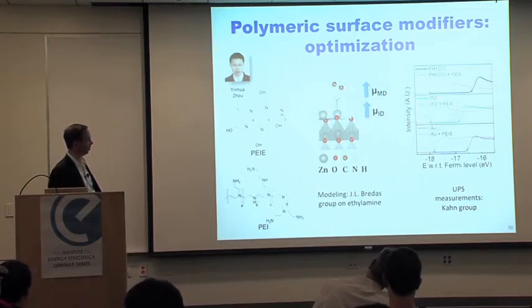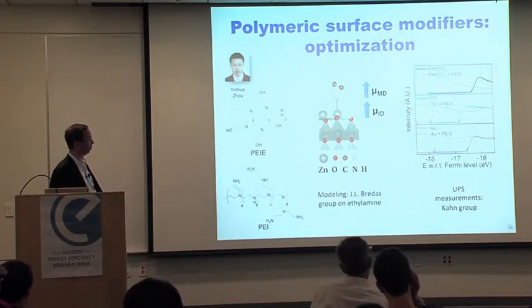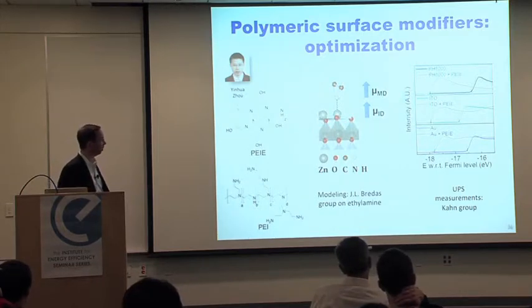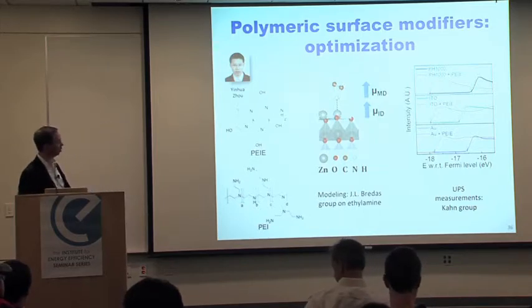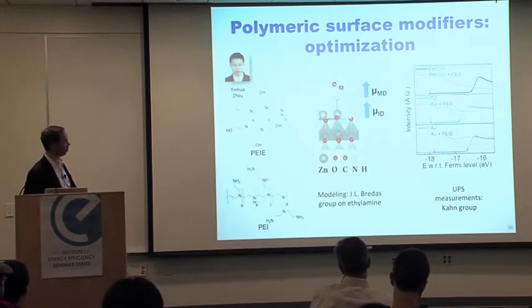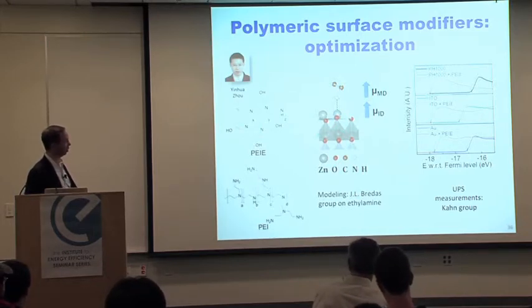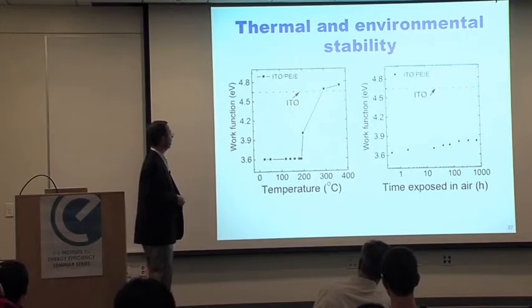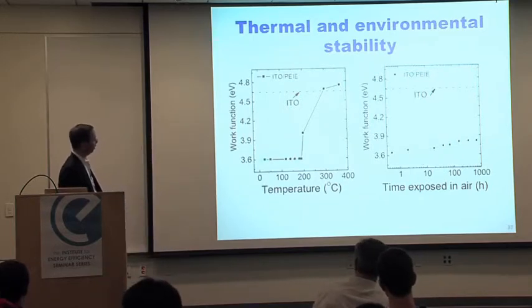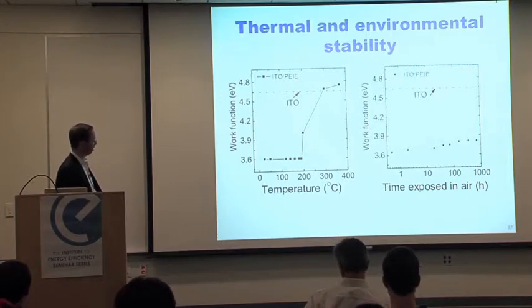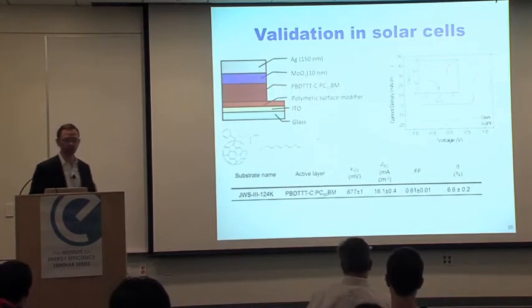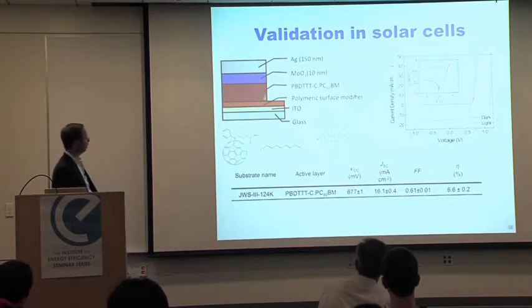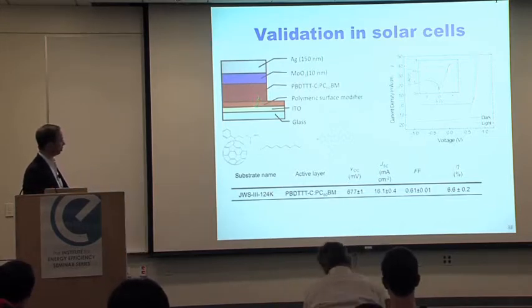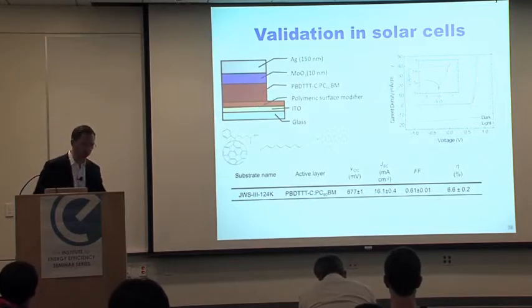And it doesn't just work on ITO, it also works on gold. It works even on conducting polymers. Okay? Some DFT calculations on some model compounds here by J.L. Bredas are also consistent with the picture that we have a partial charge transfer of these donor-like compounds onto the metal surface, and that these surface dipoles are responsible for the shifts in work function. And of course, the advantage of that technique compared to low work function electrodes is that it's fairly stable up to about 200 degrees C, and also fairly stable in air. The first step was to validate that we could use that modification of work function, decreasing the work function of ITO down to about 3.6.